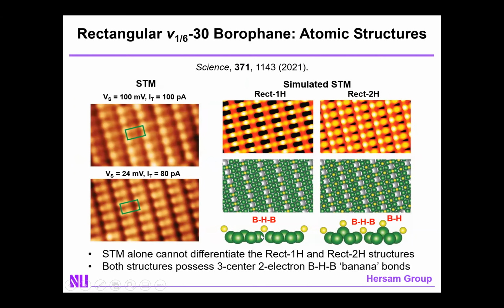In both cases, you have the 3-center 2-electron or banana bond present. But in the rectangular 2H structure, you also have the 2-center 2-electron traditional boron-hydrogen bonds present. And as a result, if we could come up with some spectroscopic means of identifying this 2-center 2-electron bond, then we would be able to conclude that the rectangular 2H is in fact the structure that we've realized.